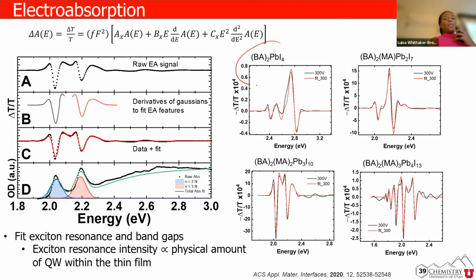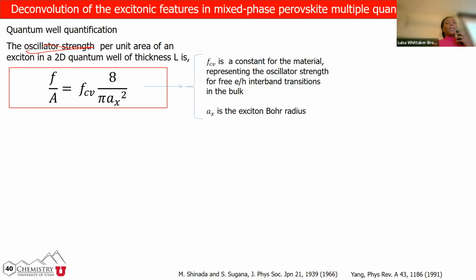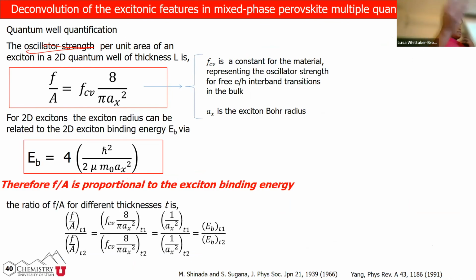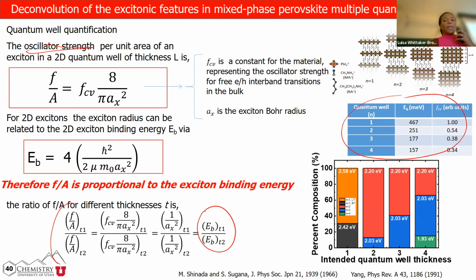Where you have different phases within the film, and then he fit the data, right? We had to take into consideration something that we call oscillator strength, and then relate that to binding energy. If we know the binding energy, then we can correlate what the oscillator strength is. We know the binding energy for single crystals. So based on his fit, he determined this percent composition right here, which tells me the amount of phases that we have within the film.